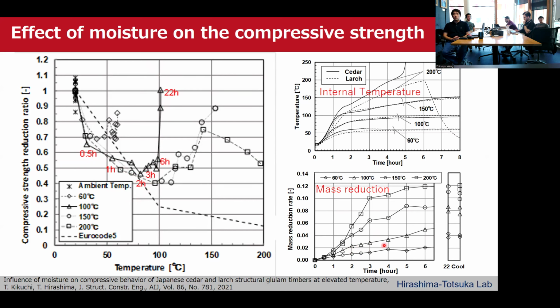When predicting the fire resistance of mass timber elements, I think that wood strength should be applied when the elements contain moisture. For this reason, the reduction ratio in Eurocode 5 is appropriate, as shown in this figure, up to 100 degrees.